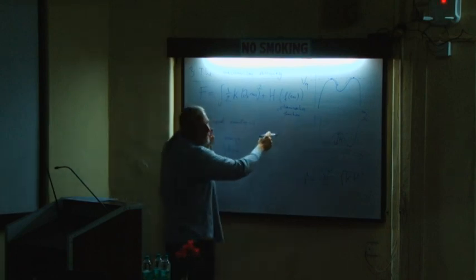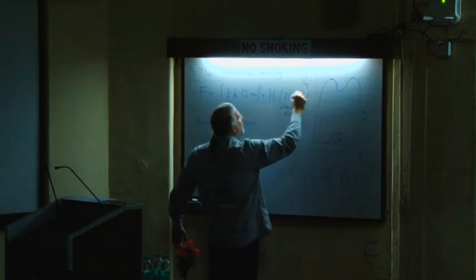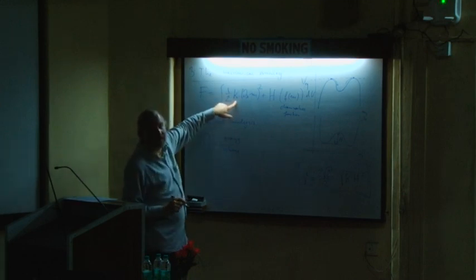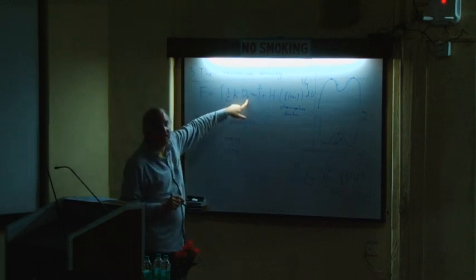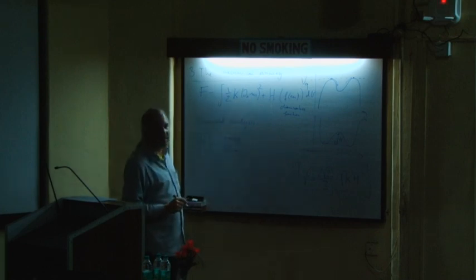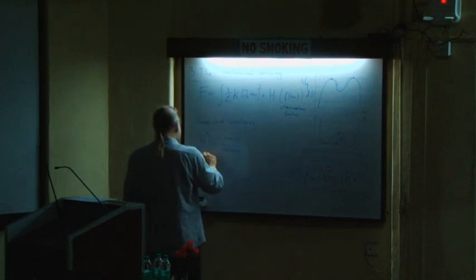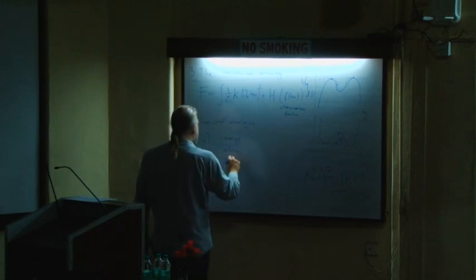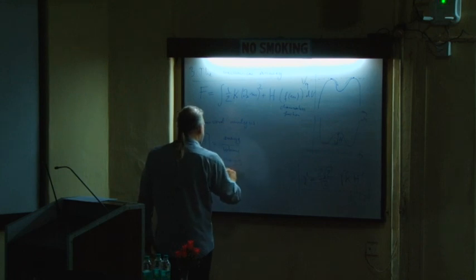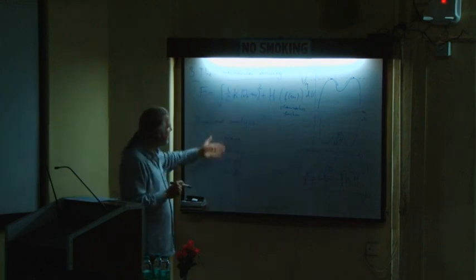because the integrand is a free energy density, right? We integrate over space, so the integrand has dimension of energy per unit volume. Here in the gradient square term, precisely, you have a gradient squared. So you take off two lengths, because gradient is like 1 over length. So the dimension of k is energy over length, because with two additional divisions by length, you get again energy.